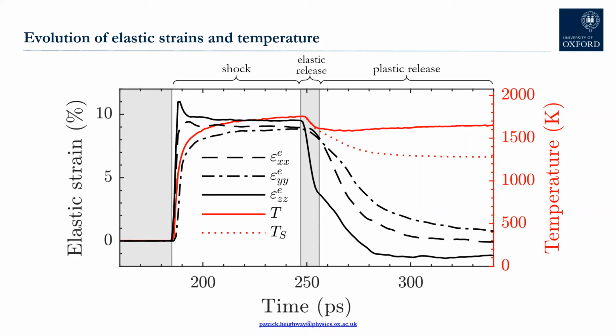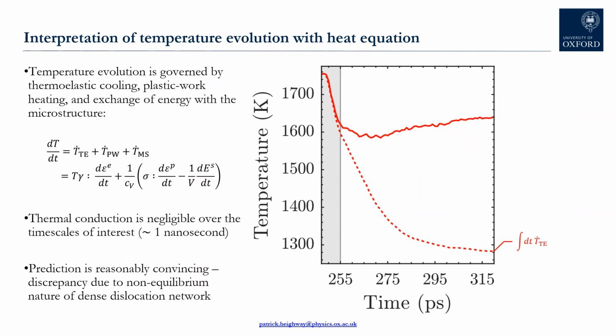For comparison, I've also plotted the release isentrope emanating from the shock state in the dotted red curve, which clearly parts ways with the actual release path immediately after the point of yielding. This is indicative of a heating mechanism that is pumping heat back into the crystal as quickly as thermoelastic cooling can remove it. So let's now attempt to interpret the temperature evolution of the material element.